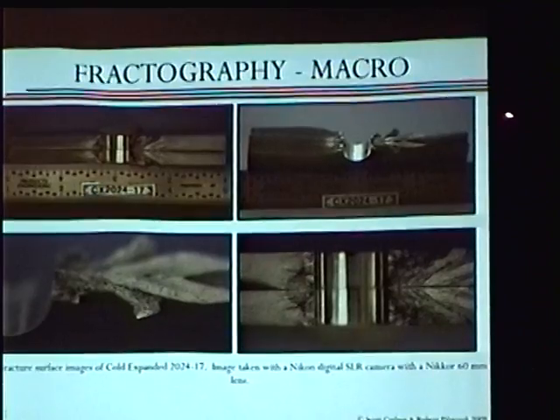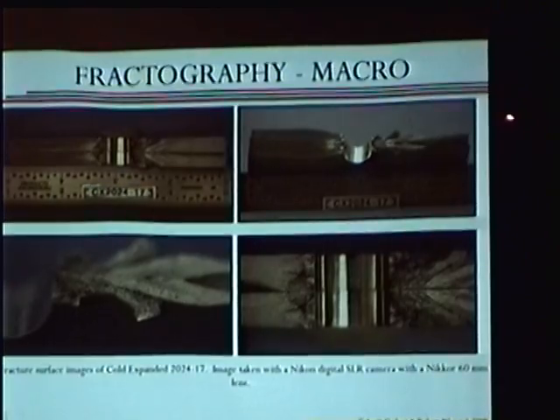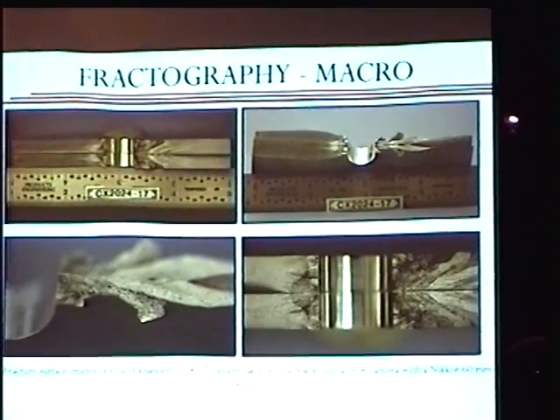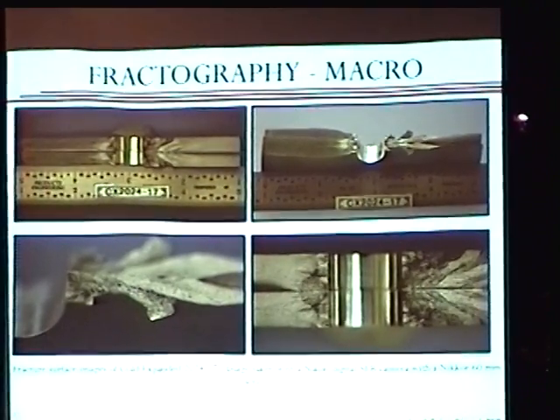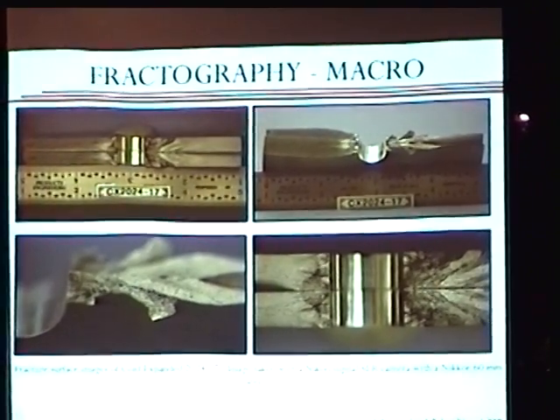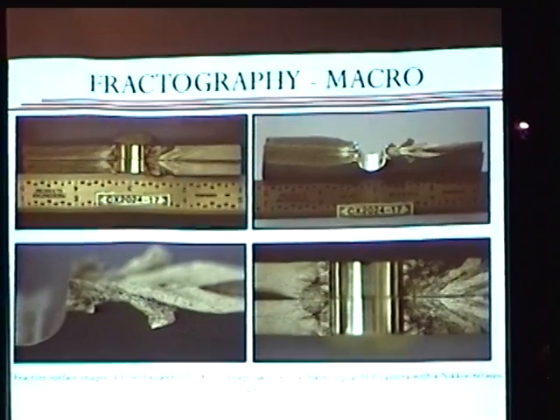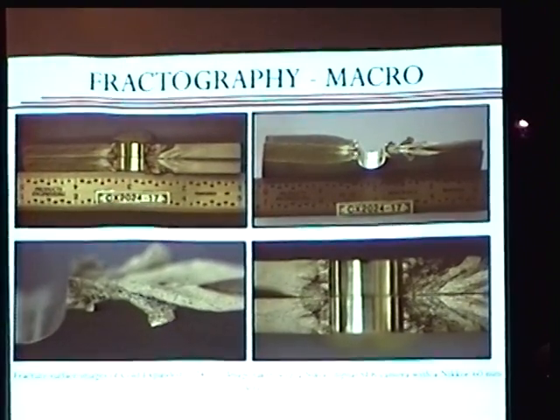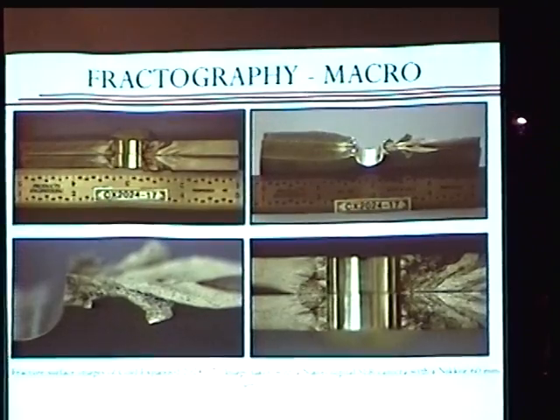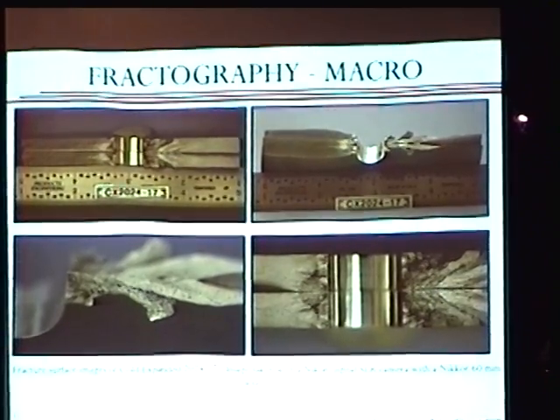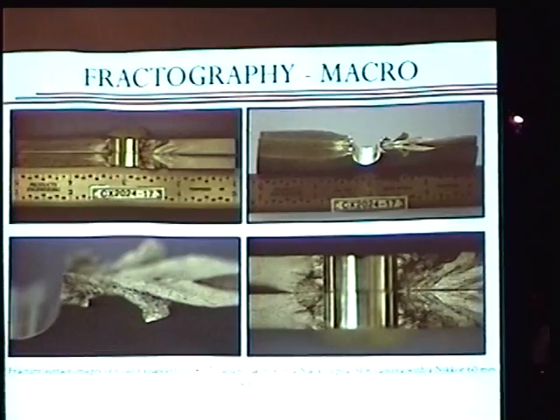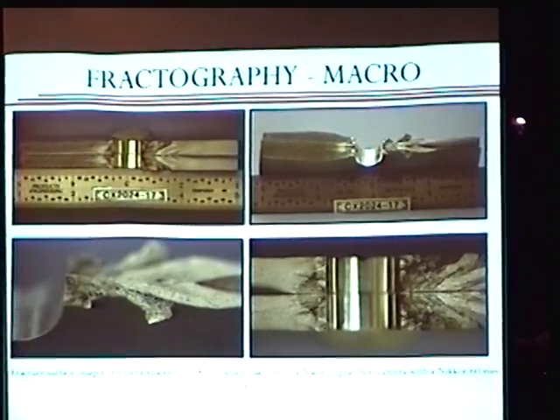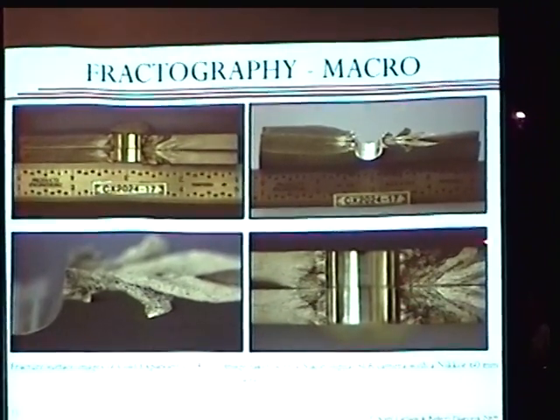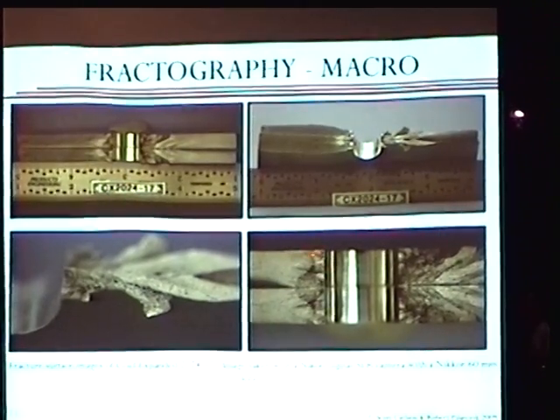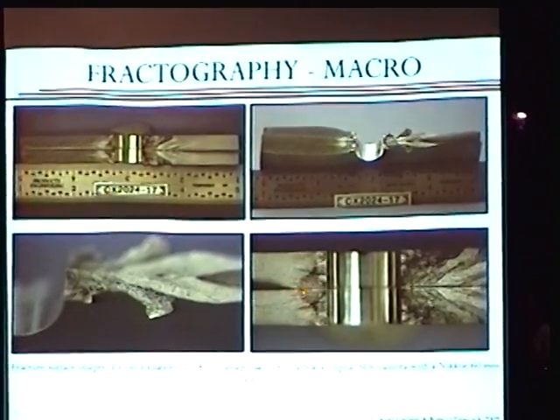So if we go to the next slide. The reason that's important: we talked about this P-shaped crack, and I showed that marker band specimen that showed how the crack propagated through the specimen. Depending on your inspection, it's not just this nice, neat, symmetric corner crack or through crack anymore. You might have a very small crack on one side and a very large crack on the other. For example, just to orient you, this is a specimen here, and it actually failed on this side, but you can see how big the crack was on the other side when it failed.